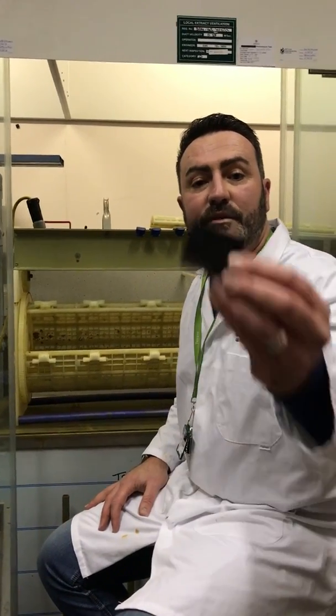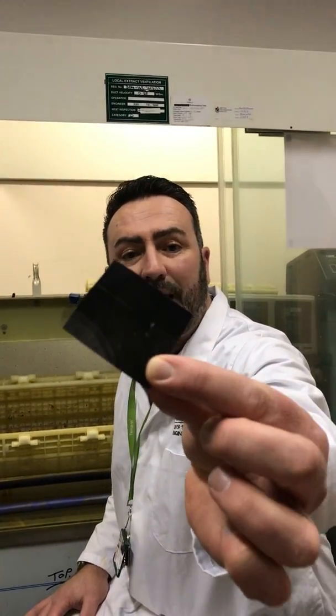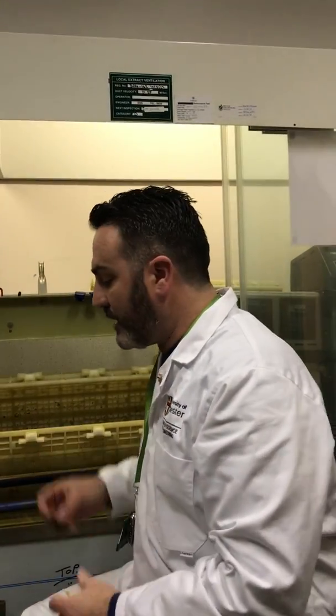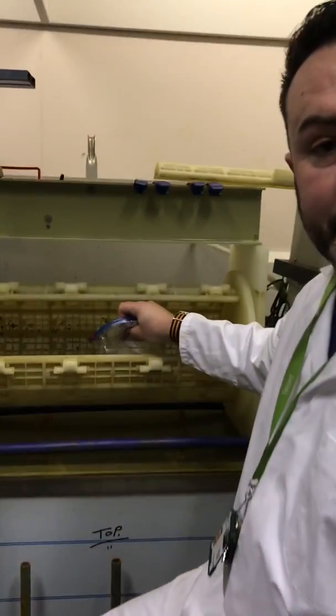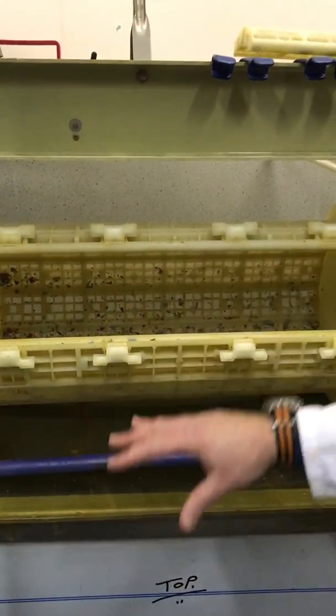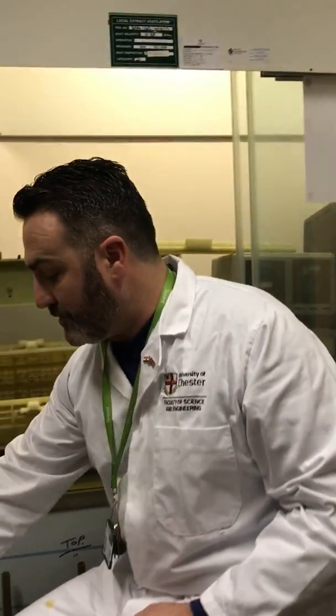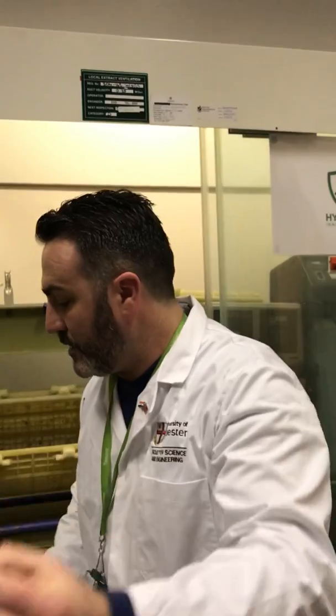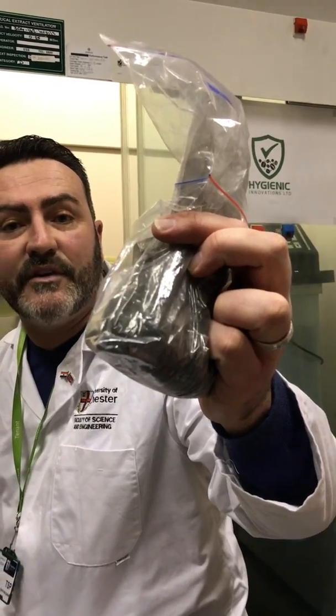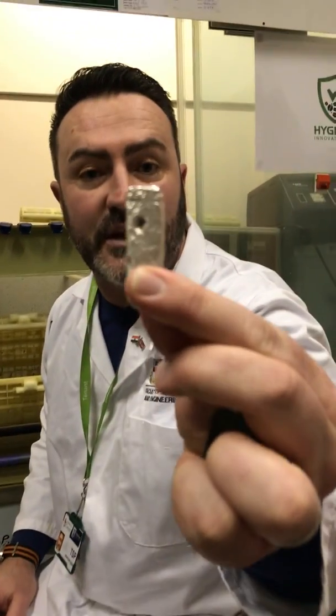We put the X-ray film, and if you have a look at a piece of X-ray, the bit that's got the black on is actually silver. So we put the X-ray film into the tumbler. We then lower the tumbler into the chemicals. We rotate the tumbler within the chemicals, and that removes 100% of the silver from the X-ray film, leaving the plastic clean. We then get a silver powder, and we put it inside a furnace and recover it as solid silver. So that is a very, very simple way of explaining how this technology works.